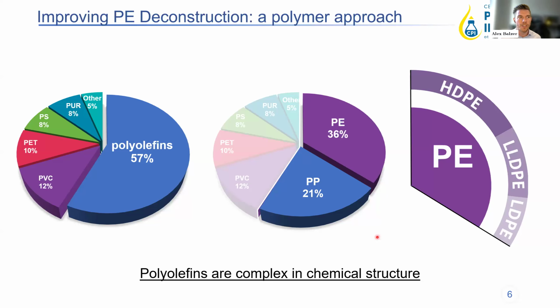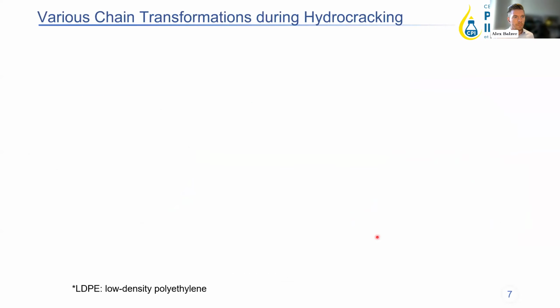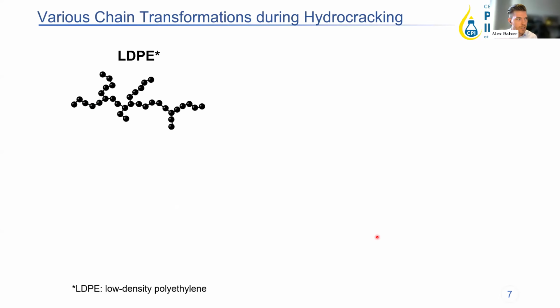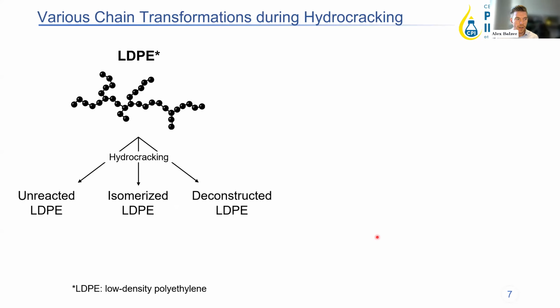Now you're going to track how this polymer changes throughout your whole reaction. So if we go back to the hydrocracking of the plastics, we took linear low density polyethylene, LDPE, fed it into our hydrocracking reactor with a particular catalyst. And what we wanted to do was first see if we could understand all the different transformations that chain can go through during the reaction. What we know from our catalyst is that the polymer chains can either not react with the catalyst, hence have unreacted LDPE in there. They can isomerize over our catalyst, and they can also deconstruct, so they can break down molecularly.